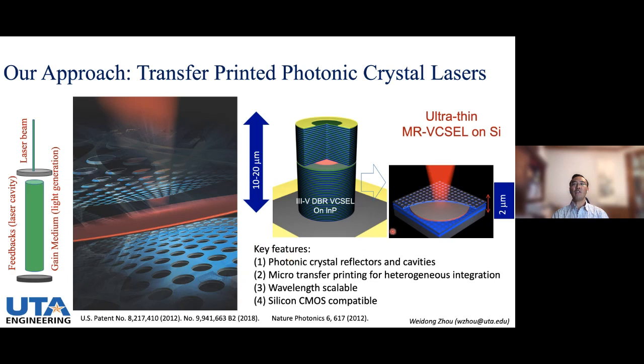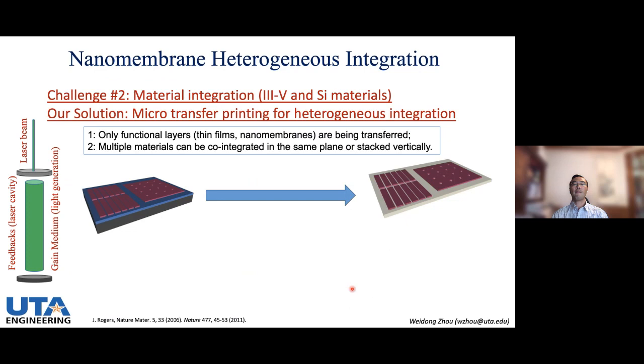Of course, we have many advantages here with the photonic crystal reflector as a cavity. I will talk about microtransfer printing shortly for heterogeneous integration, and then of course it's wavelength scalable and silicon CMOS compatible. So how do we integrate different materials together? That's another innovation we call micro transfer printing, where we put III-V material and silicon together. The idea is very simple. We typically only need a thin top functional layer to realize the functionality. The rest of the substrate is used as a mechanical support.